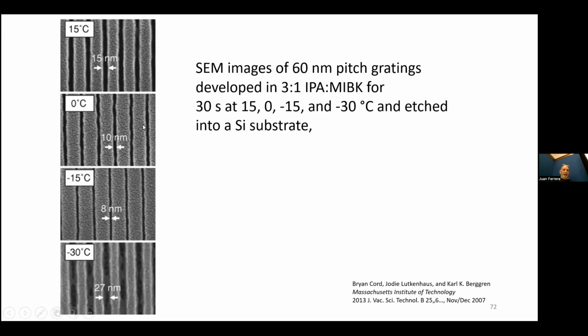And this is beautiful work that was done by a student of Hank's in NSL 10 years ago now. If we develop at 50, I can't see because my thing is in the way, but I think this is 15 degrees C up here. 15. We get 15 nanometer lines, and these are images of silicon oxide that's been etched after the resist has been exposed and developed. If we go to 0 degrees C, we get these 10 nanometer lines. At minus 15, we get these even finer lines.